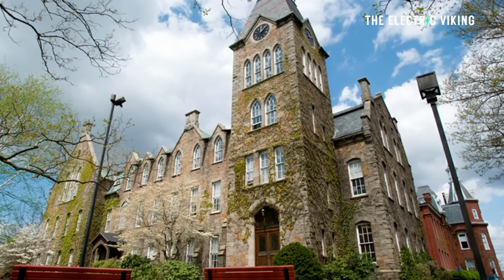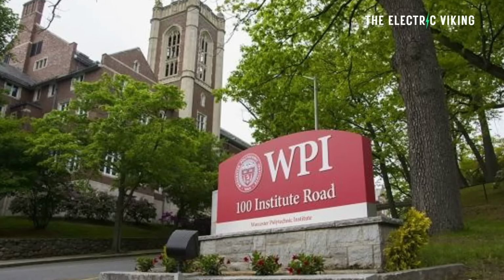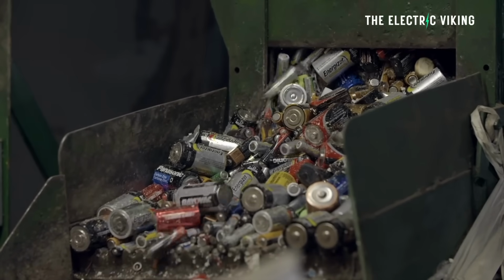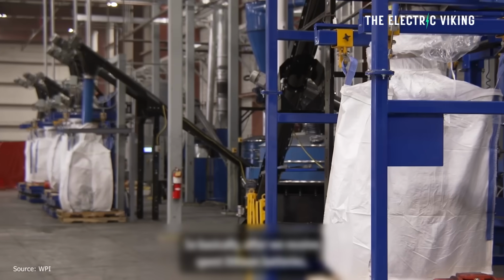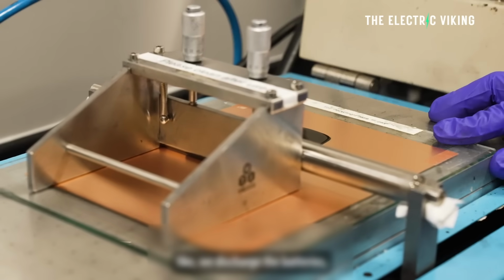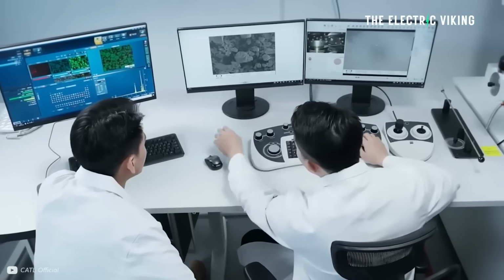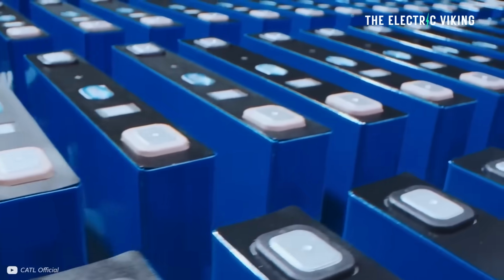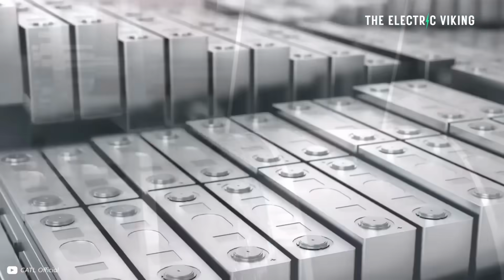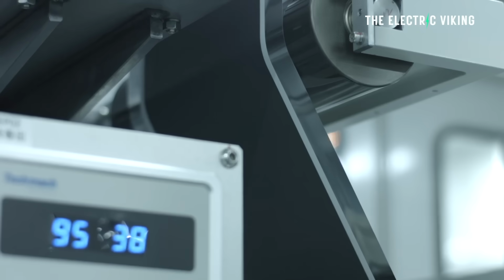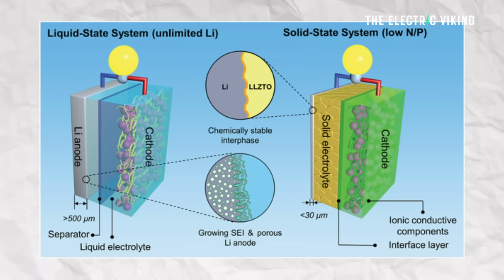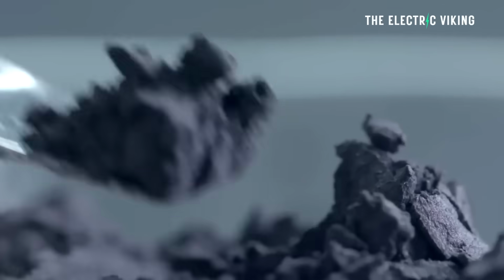A group from the Worcester Polytechnic Institute, or WPI, in Massachusetts has improved battery performance and introduced a sustainable recycling method. Led by Professor Yan Wang, the team focused on improving solid-state batteries. These batteries are considered a safer and more stable replacement for conventional lithium-ion batteries. They developed an iron-doped material, and this newly developed material simplifies the design of next-generation solid-state batteries. It addresses a big issue with solid-state, the incompatibility between halide-based solid-state electrolytes and lithium metal anodes. This issue is generally solved by adding protective layers, but those layers increase the cost and complexity of the batteries and can sometimes lead to quick degradation.